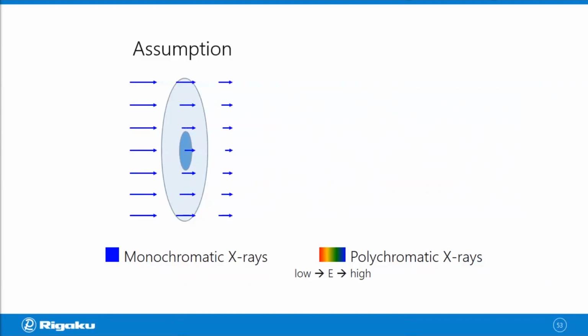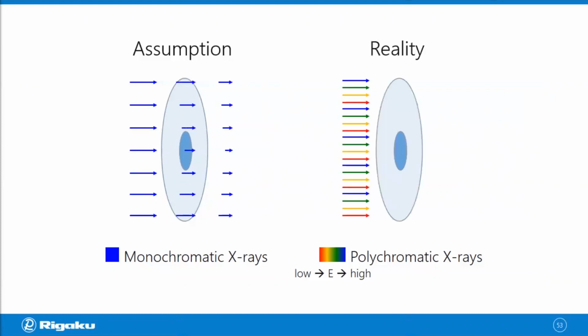But the reality is, you have polychromatic X-rays coming in, and higher energy X-rays can get through the sample better compared to lower energy X-rays. What that means is the energy distribution of those X-rays shifts towards the higher side as they go through the sample. And high energy X-rays are also called hard X-rays. So you can say that the incoming polychromatic X-rays' energy shifts towards the higher side as they go through the sample, which also means X-rays harden when they go through the sample. And that's where the term beam hardening comes from.